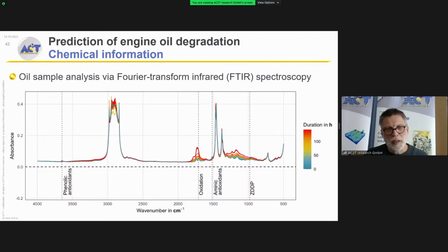The chemical information is obtained in this case using Fourier transform infrared spectroscopy, which measures absorption bands. This is a very well-known procedure in lubricant chemistry, and the experts in the chemistry department can assign certain products of the lubricant to certain bands in this spectrum. And this information should be used to devise some quantitative correlation techniques.